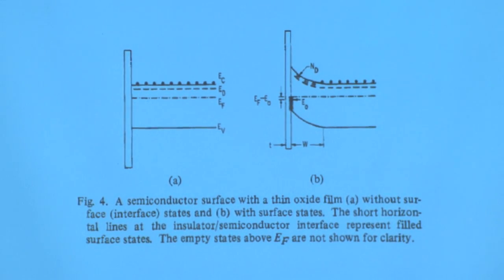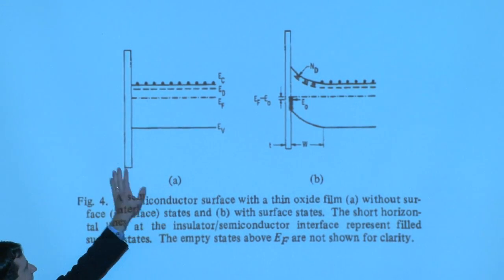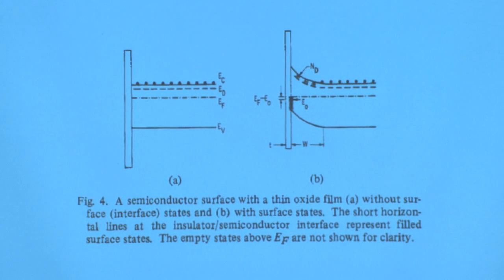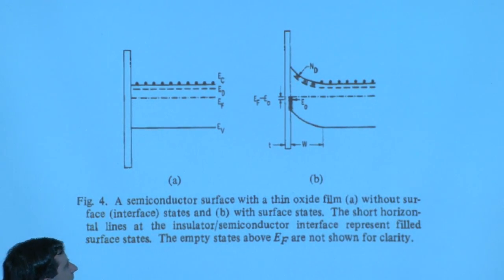And so if there are no interface states, if we have an ideal material, we have our semiconductor over here and our surface layer there, and at that interface, boom, you just have a discontinuity in the conduction bands. And of course, the vacuum levels are matching up. But in the case where you have surface states at that interface, what happens? Well, now those surface states can be filled by electrons in the neighboring region. And as a result, you'll have a natural band bending at that interface.